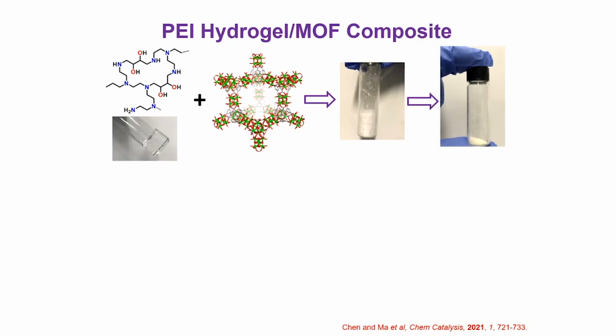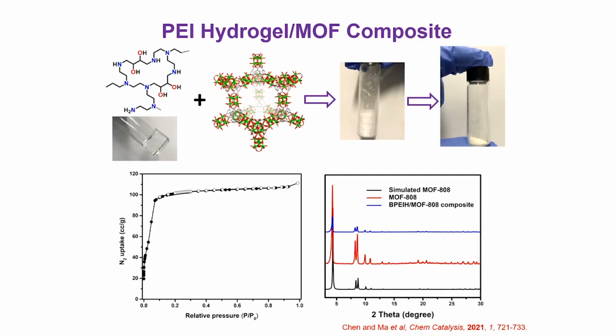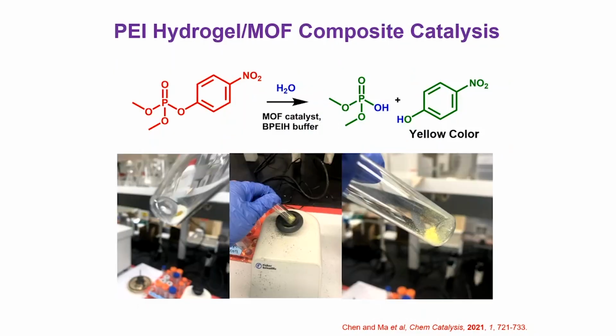When you mix it with the MOF, you could make that powder. But more importantly, you could maintain its porosity and its crystallinity. That means we're not blocking, because that's the main thing. When you coat a MOF with a polymer or a hydrogel, one of the things you are worried about is things blocking the entrance to your materials, and then you lose the effectiveness of that material. And in this case, we don't.